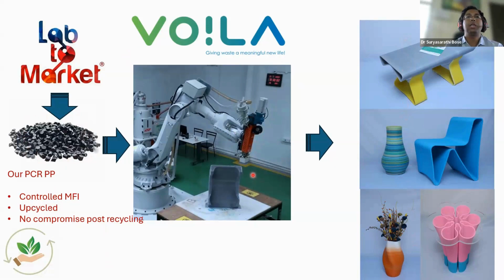And in order to print it, they need a strict MFI band of 5 to 8, while the PCR that we received from the market had about 30, which means they flow very easily. But in order to print them, you need material that has a count between 5 and 8, which means they should have the right viscosity so that you can print them into products. Since with our PCR we were able to control the MFI, and at the same time improve the structural properties, we were able to print them into various products. And these products very soon will hit the market, and they are sleek and elegant, and they can compete anytime with the products that are out in the market.